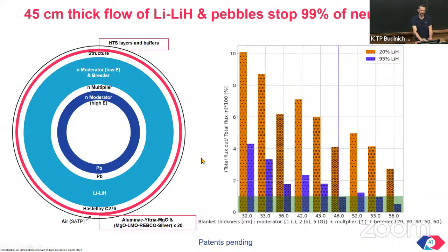Now, our material is a solution of lithium and lithium hydride. So lithium is needed for the breeding of the tritium, as you saw before. And it's a very good absorber of neutrons at low energy, but a very lame attenuator at high and medium energies. So if you follow the history of a neutron in a layer of lithium, what happens is that a long distance is traveled for the neutron to gradually slow down, and finally, in a few centimeters, it is absorbed.